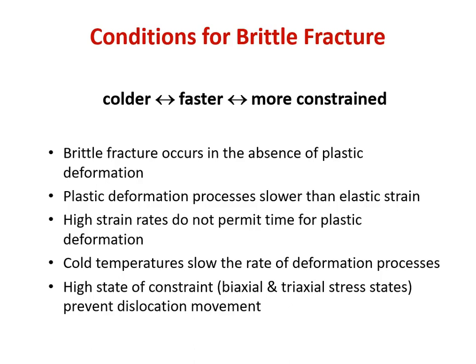And all of these conditions are 100% relatable to how easy it is for the material to deform instead of simply forming a surface in order to accommodate the imposed stress, especially stress near the tips of those pre-existing flaws. So you can think about the conditions for brittle fracture as being the conditions that make it difficult to move a dislocation or slip a polymer chain. And I have a little three word memory aid for this. I usually call it colder, faster, crowded. And another way to consider crowded is more constrained.